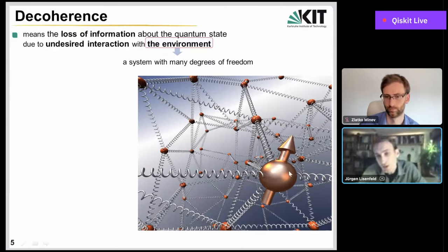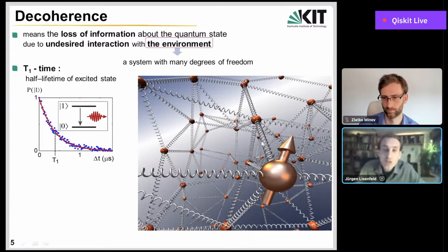If you have some excitation in the qubit, this energy may find a way to the environment, which means that the qubit would spontaneously decay back to the ground state under emission of its energy, as if in the form of a photon or phonon. And if you measure many qubits, you would find a half lifetime for this decaying state, the so-called energy relaxation rate, or the inverse T1 time. This T1 time is one of the most important figures of merit for these qubits. You want to have the T1 time as high as possible, because this limits the time during which your qubit stays coherent, so during which you can do reasonable quantum calculations.